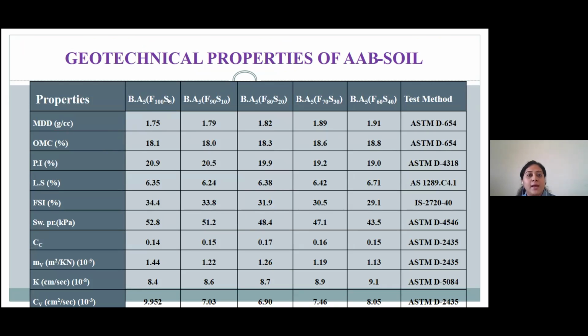F100 means 100% fly ash, S0 is 0% slag. B is black cotton soil, A is alkali activated binder, 5 denotes 5% alkali activated binder. So we have maintained 5% alkali activated binder, but we have varied fly ash and slag in the ratio 100:0, 90:10, 80:20, 70:30, and 60:40.